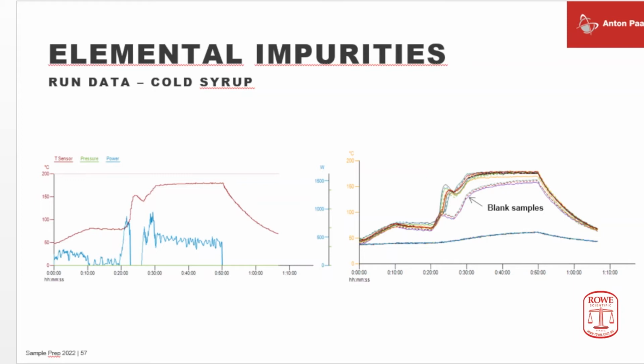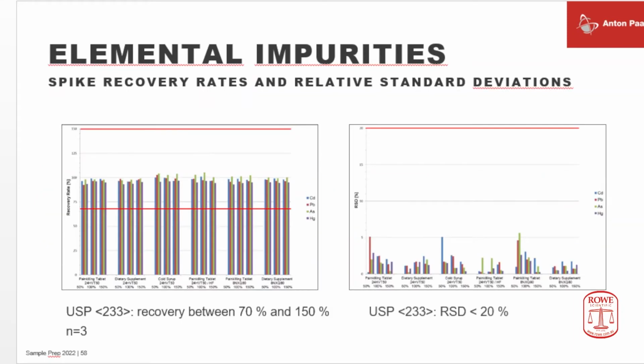When we look at the spike recovery elements, and this is a little bit hard to read, for the elements cadmium, lead, arsenic, and mercury, you see that the recoveries, which USP says must be between 70 and 150, this is a very wide range. In fact, we managed to be at around 100 plus 2 or 3, minus 5 to 6% recovery. And this is indeed very good.